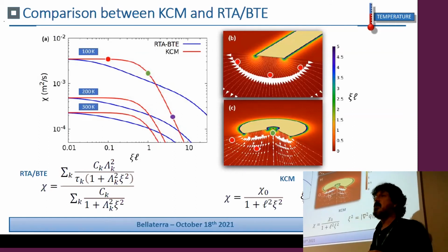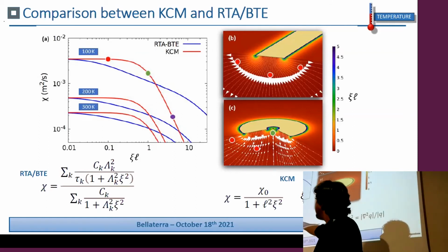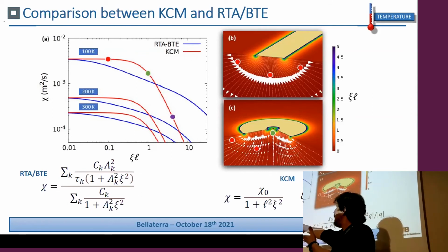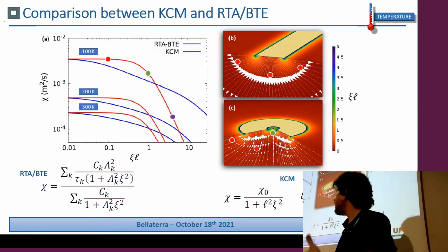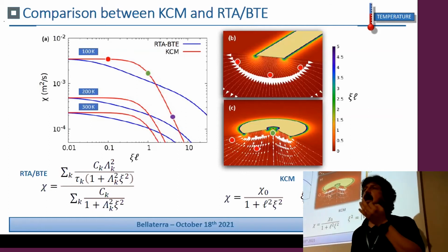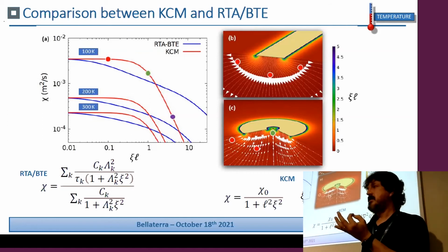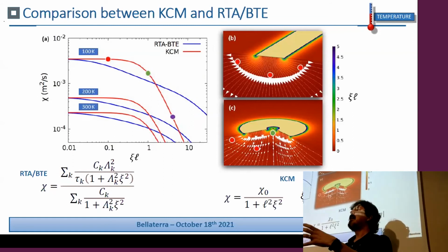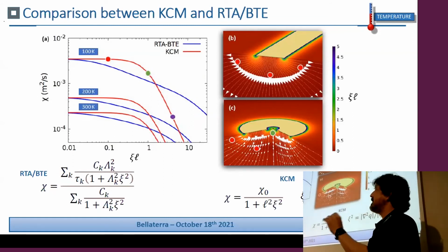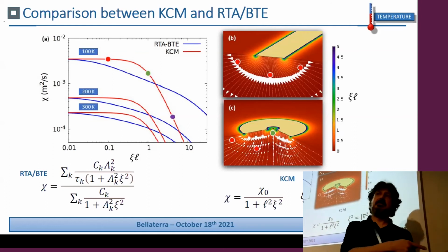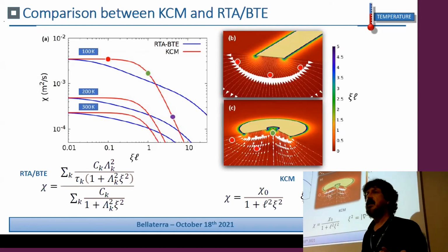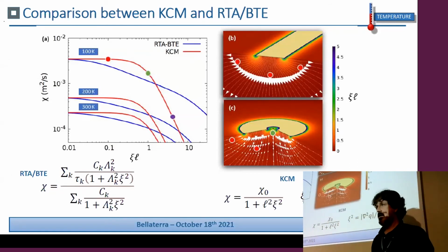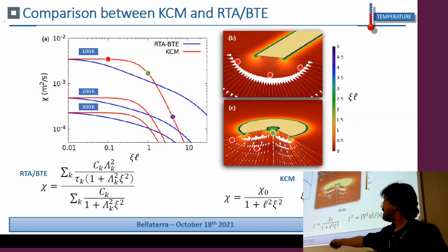But if you're doing it with silicon at 300 Kelvin, you will get a reduction. These are not length scales, but believe me, you will start to see effects from this theoretical point of view from 30 microns. 30 microns means that if you have something that is 30 microns, you should observe a reduced thermal conductivity. And this does not agree with what we have seen. The point where you start to see some changes is at 1 micron, not at 30 microns, as this theory predicted.